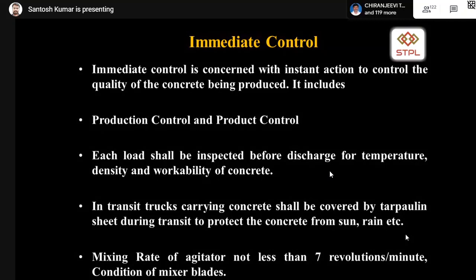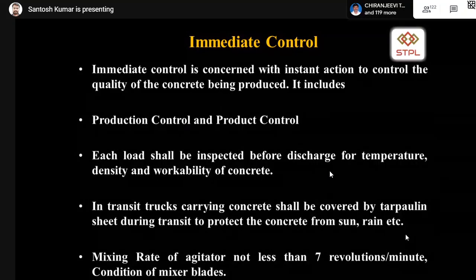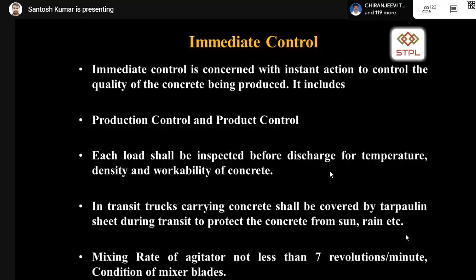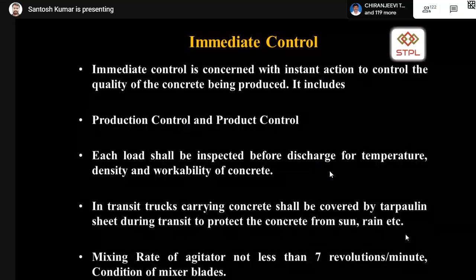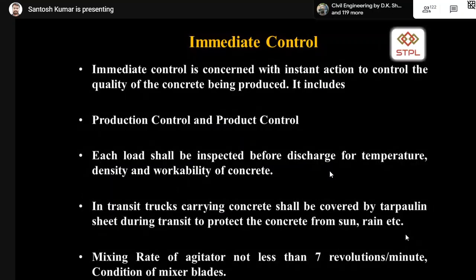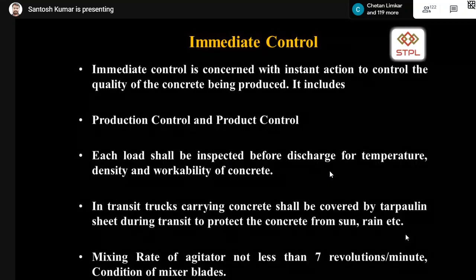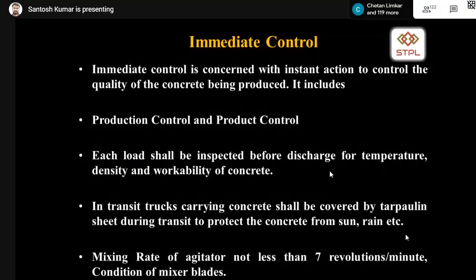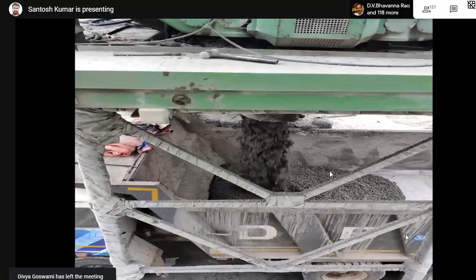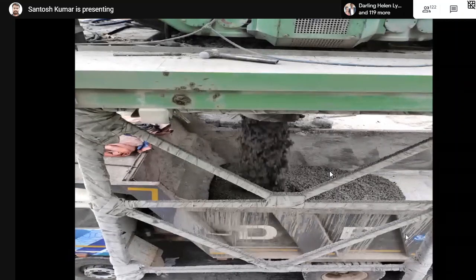And when it comes to the agitator or the transit mixers, a minimum of 7 revolutions per minute is expected from a transit mixer when it is in loaded condition. Actually, if you see in practice, a new RMC transit mixer can rotate up to 14 revolutions per minute, but the standard expects a minimum of 7. And the wear and tear of the blade should be checked frequently. And this comes under immediate control, before the concrete is placed at the site.